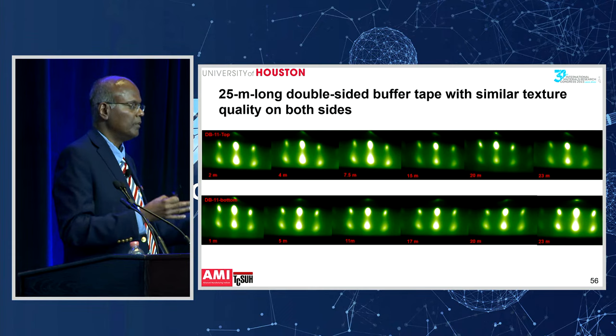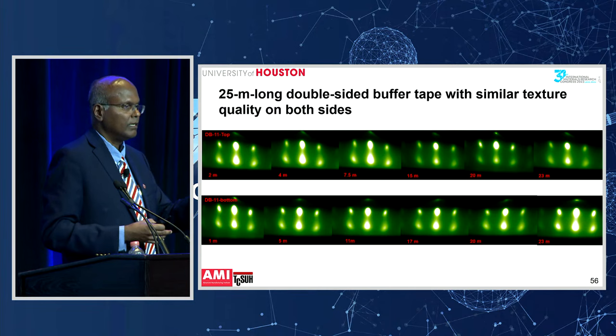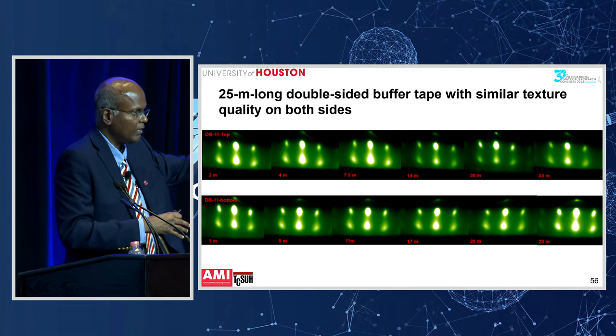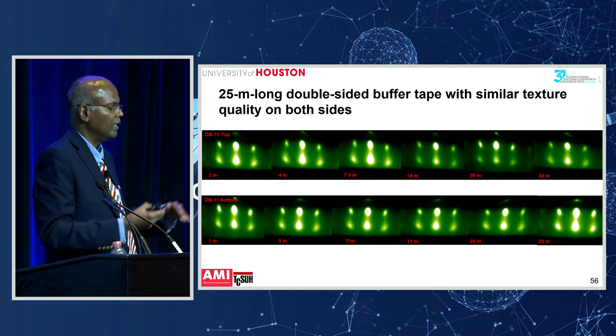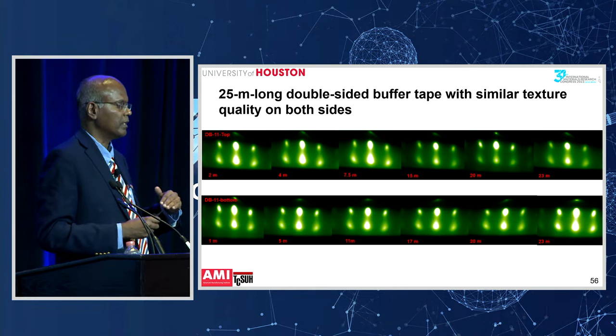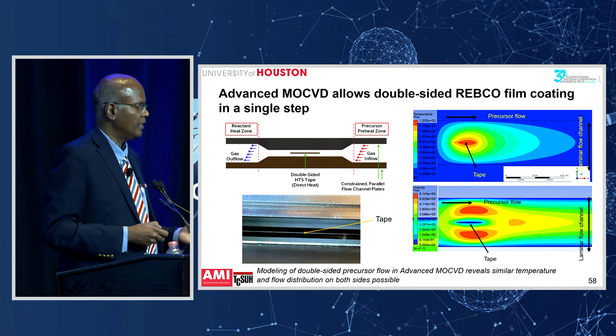And the texture can be monitored in real time with the RHEED, and I'm showing the RHEED patterns on the top side of the film on the top row, and the bottom row is the RHEED patterns on the bottom side. And you can see a good texture obtained on the buffer layers on top side and bottom side. And now if you take that film and grow it in the MOCVD, I'll skip that, lack of time.